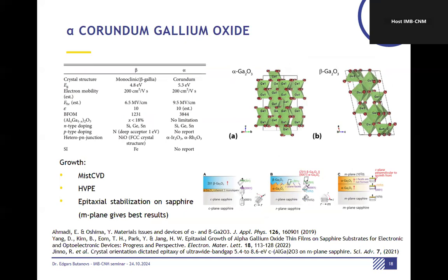So what people typically do is use more kinetic processes, such as mist CVD. That's an interesting technique the Japanese demonstrated, and now it's being employed quite nicely. It's a high growth rate method, similar to halide vapor phase epitaxy, which also makes it possible to grow alpha phase gallium oxide. However, if we talk about classical methods, I don't think I've seen MOCVD growth of alpha phase gallium oxide, but you can induce this phase growth by epitaxial stabilization. You can do it with pulsed laser deposition, MBE, physical methods, let's say, and also sputtering. And typically you need to select a very nice lattice matching substrate. The best is M-sapphire. It gives the best results due to the specific growth mechanism of how the alpha phase grows on corundum sapphire.